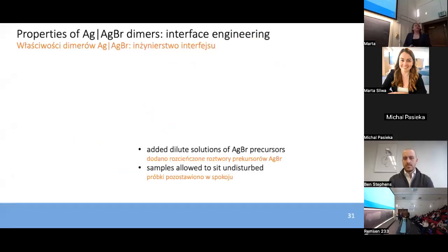So we started with that first option, growing or trying to deposit a material on that host, the silver particle at the 111 facet. And we hypothesized that if we added dilute solutions of silver bromide precursors and allowed the samples to sit undisturbed, we call this an incubation process, that perhaps we could deposit silver bromide again on that 111 facet and potentially control.